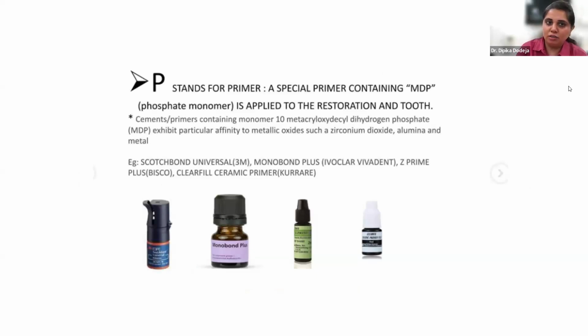As I said, the phosphate group bonds to the oxide part of the zirconia. So the cements containing monomer 10-MDP exhibit particular affinity to metallic oxides such as zirconium dioxide, alumina, and metal. So the phosphate group of the MDP bonds to the oxide group of the zirconia. There are various primers available in the market. The 3M Scotchbond Universal has an incorporated MDP, which is a universal bonding agent.